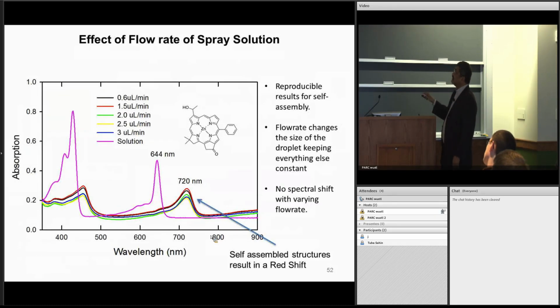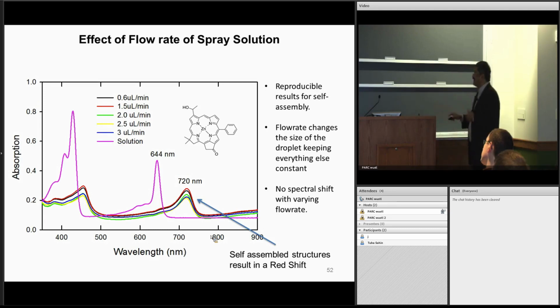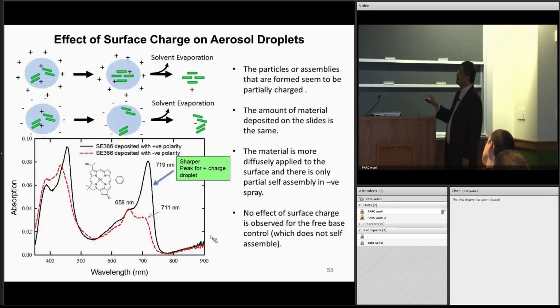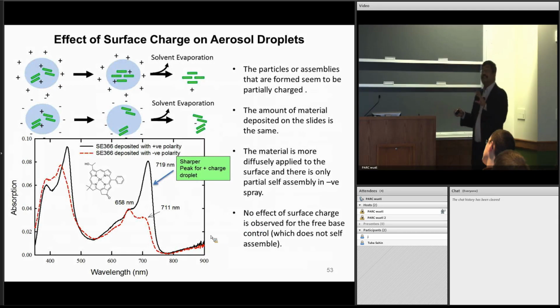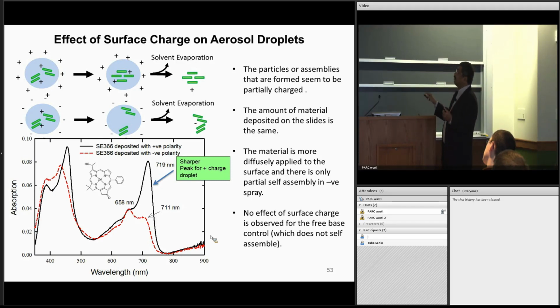And this just shows that these assembled structures are indicated by a red shift in the absorption spectrum. So these are the monomers, these are the various concentrations. You can play with the concentration, which will then control the kinetics of self-assembly and so forth. Here I just show you the effect of charge. I can change the charge on the droplet, right, by just switching the polarity.